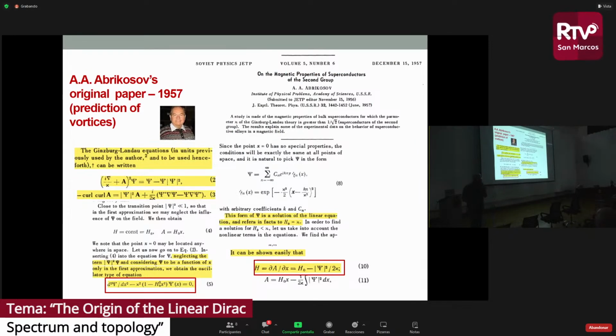You go back to 1957, and you look at Abrikosov's paper that gave rise to vortex physics. Okay, what he does is to solve the Ginzburg-Landau equations. But when you look in detail, he solved them in a very particular way. Inside the Ginzburg-Landau theory, he found two equations. Here you have the ground state of the harmonic oscillator. This essentially is a particle in a magnetic field, okay? But he looked at the ground state equations for that. And once he finds the order parameter, he obtains the local magnetic field by taking psi squared and the applied field.